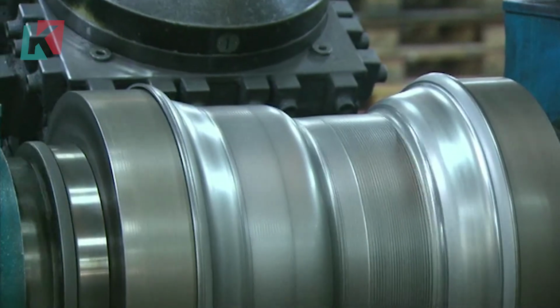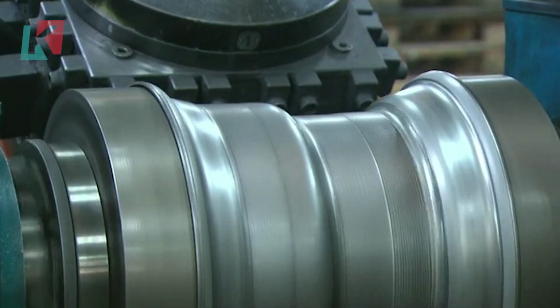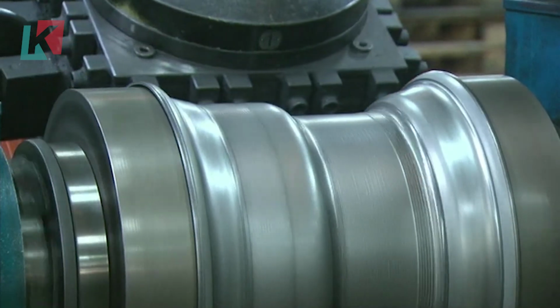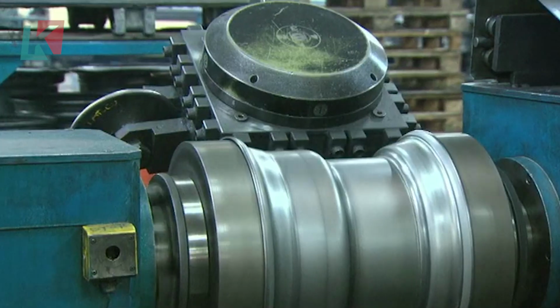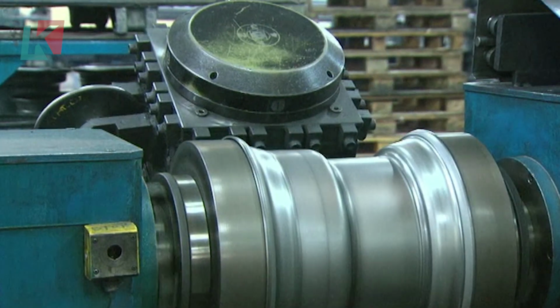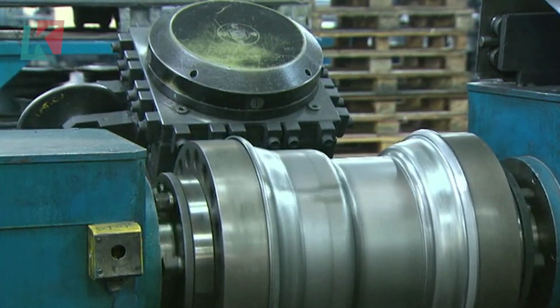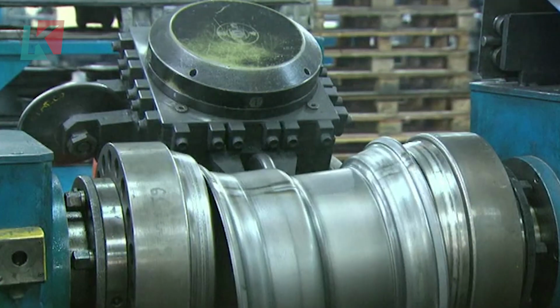The rim welding process uses specialized resistance welding equipment. The wheel rim and center section are joined using precisely controlled electrical current that creates a molecular bond between the steel surfaces. This weld joint must be stronger than the base material itself. Quality control testing actually proves this by testing sample welds to destruction.